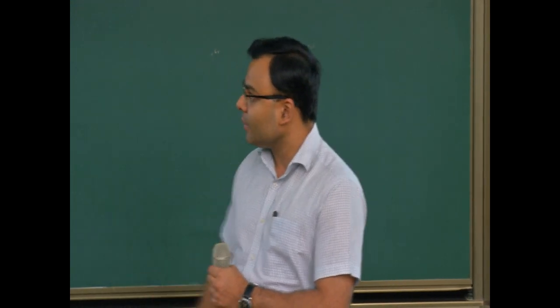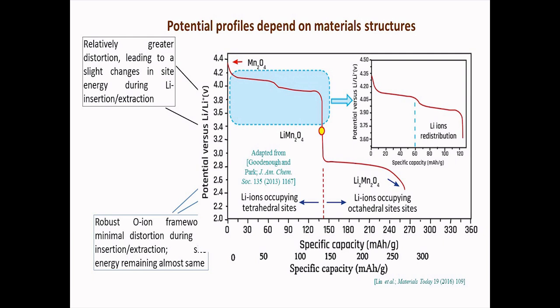Now, I talked about the site in which the lithium is going in. As one can see, same material, LiMn2O4, going from Mn2O4 to LiMn2O4 to Li2Mn2O4. The transition metal redox, which leads to the charge compensation when the lithium is coming in, is Mn3+ to 4+. In other words, all the electrons which are coming are going into the Eg band of the manganese 3d oxygen 2p orbital. So that remains the same.